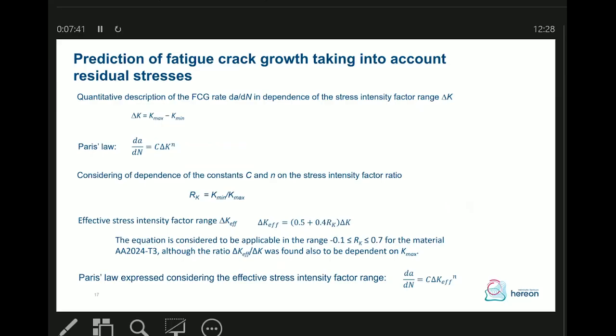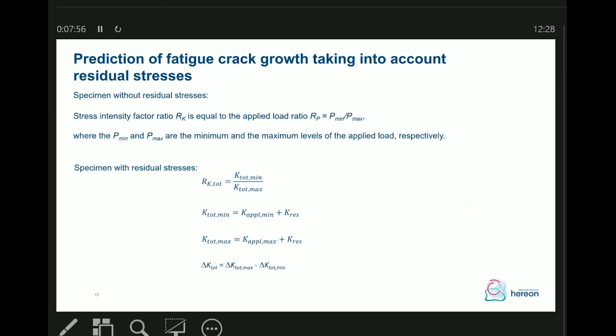We can also introduce the crack closure effect. The idea is that we use Paris law with the effective stress intensity factor and identify the parameters of crack closure due to the presence of the continuum. And how can we do it?